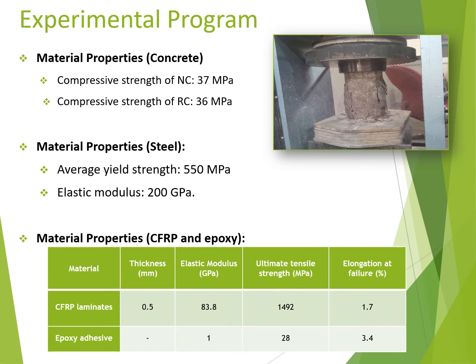As for the steel, tensile tests were conducted on the 8 and 12 mm rebars, and the obtained average yield strength was 550 megapascal with an elastic modulus of 200 gigapascal. The table here shows the material properties of the CFRP and epoxy used in the study. The CFRP laminates had a design thickness of 0.5 mm with 83 gigapascal elastic modulus and 1,492 megapascal ultimate tensile strength.